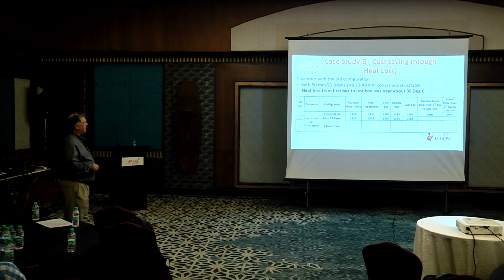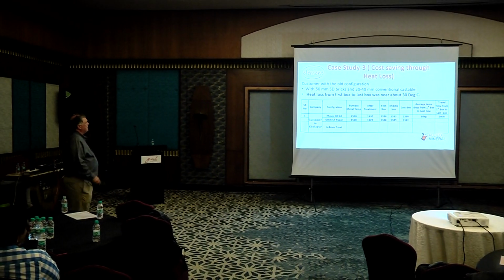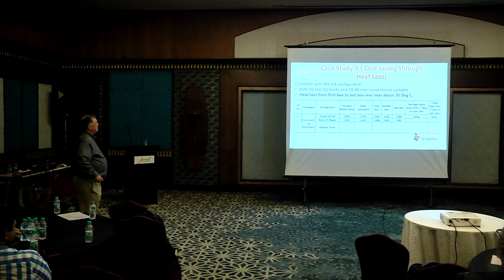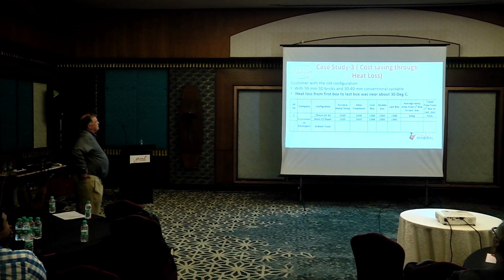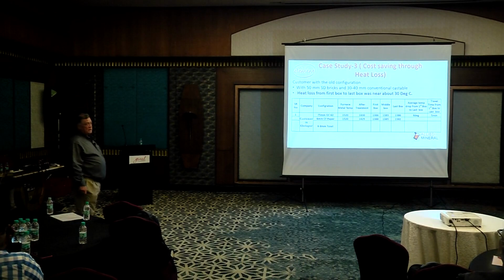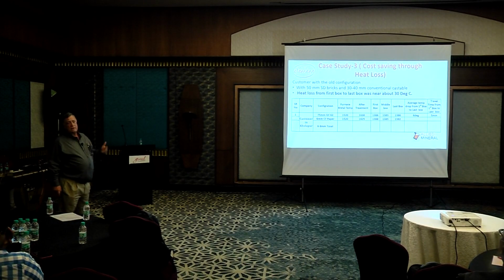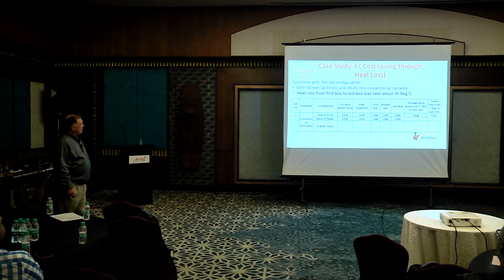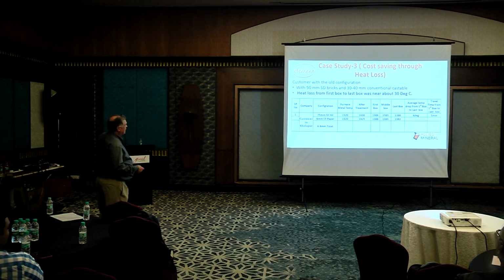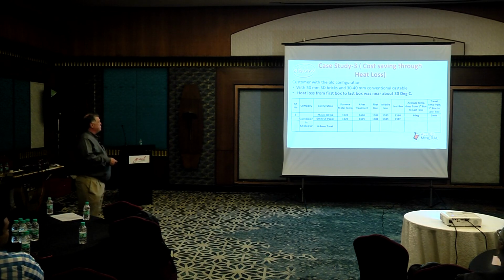Again, here's case study 3. Customer with the old configuration with 50 mm Super Duty bricks and a 30 to 40 mm conventional castable. But again, most likely, they're sifting this so they can get a finer grain so they can install it better. And if they're not, they're increasing water content, which is really affecting their lining life. So here they have 75 mm quick cast 62, and they're showing also one where they put paper.